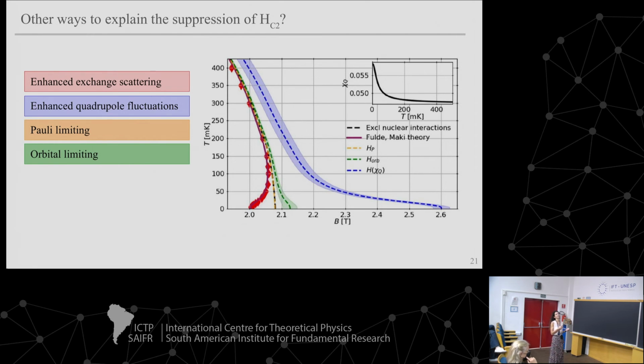We also considered a modified Pauli limiting or a modified orbital limiting because of the change in behavior of the system at low temperature. Orbital limiting would enhance the superconductivity very weakly. Pauli limiting would suppress it, but so slightly that you don't really see the difference from the original, predicted, unmodified one. So none of these things can explain the relatively strong suppression that we see. So we think that this is really the right explanation. Of course, there may be other scenarios that we haven't considered, but these are the ones that we did consider.